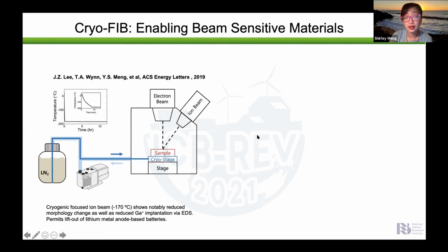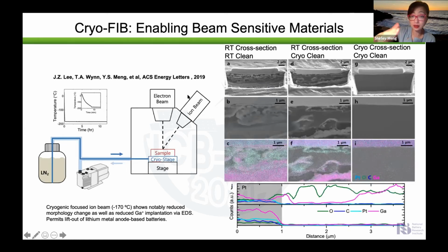So if you look at the cross-section imaging of the lithium, so typically when you have a lithium piece, you have to cut the cross-section. If you cut the cross-section with a gallium ion beam at room temperature, you're going to see this is a lithium foil, right? You can see a lot of very strange features, and these features are indeed coming from the gallium and the lithium interaction. So the challenge for observing lithium metal is really lithium metal reacts with everything, including the gallium. So the trick to go around it again is to turn it into cryogenic method, where you can then very nicely preserve the microstructure of lithium metal.